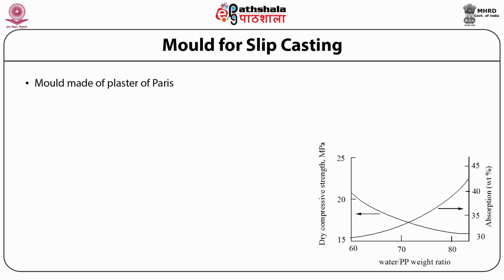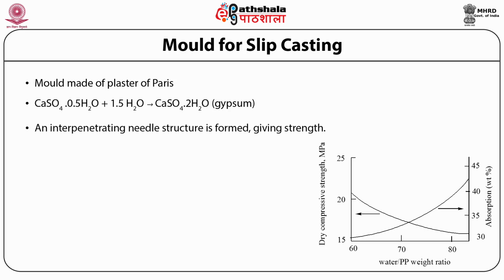The mold is commonly made from plaster of Paris, that is PP, which is partially hydrated calcium sulfate. On addition of water, it gets hydrated to gypsum, and the equation is written as follows: CaSO4.0.5H2O plus 1.5 times H2O gives CaSO4.2H2O, which is gypsum. The gypsum forms in the form of interpenetrating needles and plates and produces a mold with adequate strength. The water to PP ratio according to the above reaction is 18.6 by 100.